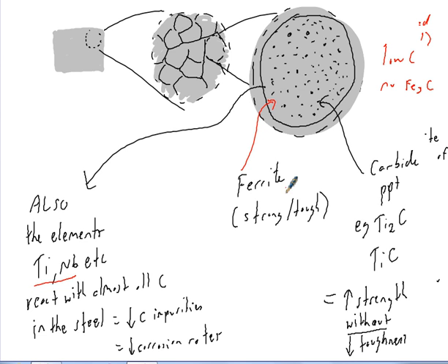is ferrite, which actually has only a very, very small amount of carbon, because most of the carbon is now inside these things called carbide precipitates. Because the titanium, niobium, zirconium you add reacts with carbon to form these compounds of carbon, and they scatter throughout the whole structure. Rather than being those layers we saw before, we get these tiny spherical-like particles of carbides all throughout the steel. And these are strong, so they increase the strength of the steel, but because they're not in layers, they don't decrease the toughness.